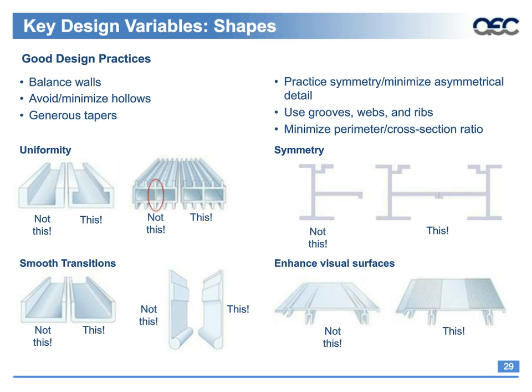Looking next to that, the shape with all the fins on it, a designer may look at it and say, hey, I just need a separation between these two voids in this hollow extrusion, so I'm going to make that wall as thin as I possibly can. That's easy to do in extrusion, but it's even easier to extrude it with more consistent walls where you can. The shape will extrude slightly faster. So sometimes working with an extruder, you may find that the weight savings from that red circle that says not this is overcome by the little bit faster extrudability you can get out of the next one.